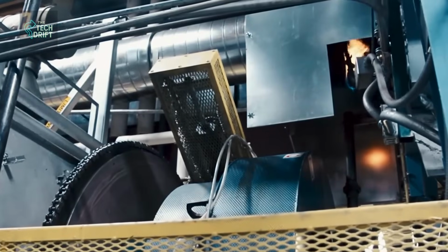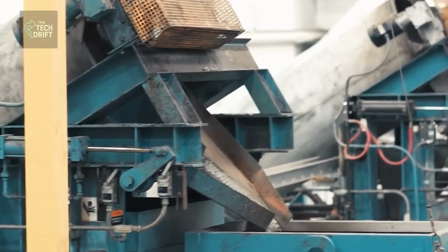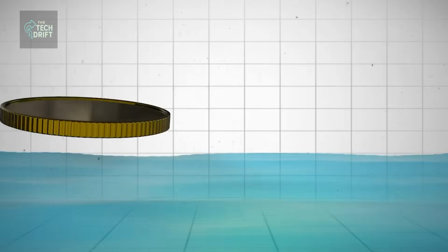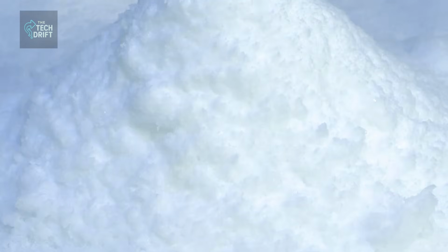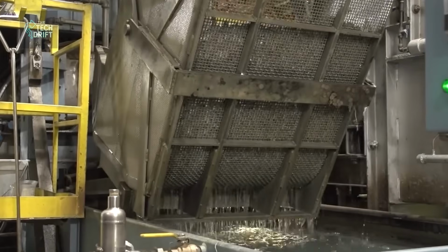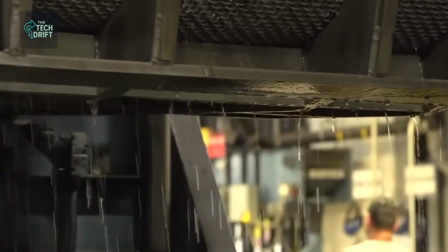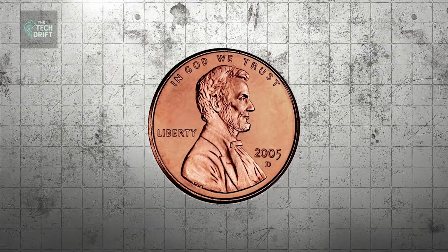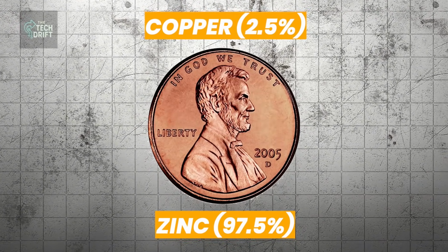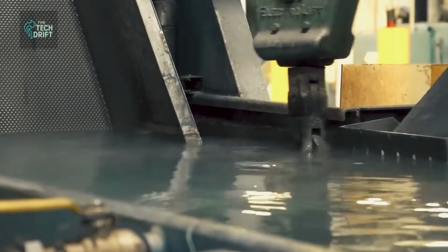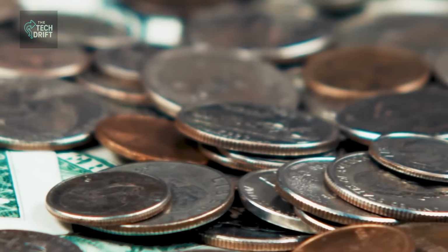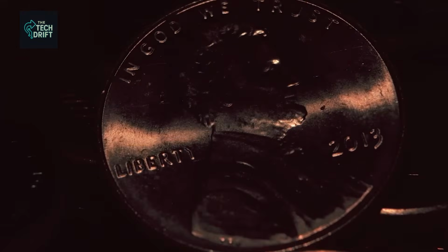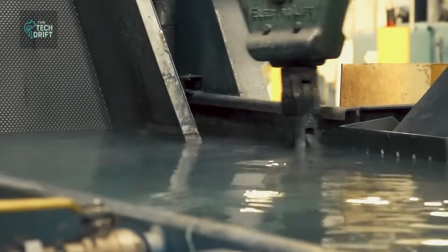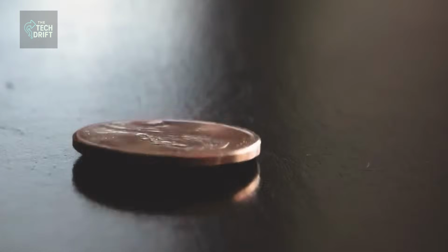The instant they leave the hot zone, the disc must be quenched, not in plain water, but in a carefully formulated bath designed to protect the surface and keep the metal from sticking together when it's most vulnerable. The quench bath isn't just water, it's formulated with citric acid, added as a powder, not from actual fruit. The acid loosens surface grime so the blanks come out clean, and it's especially important for pennies, which have zinc cores covered with about 2.5% copper on top. It removes the thin layer of copper oxide without attacking the metal itself. That's why newly made cents leave the mint with that bright, just-struck shine. The bath also includes lubricants that keep the still-hot planchets from sticking or welding together during cooling.